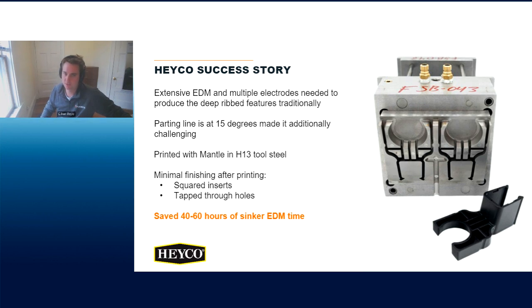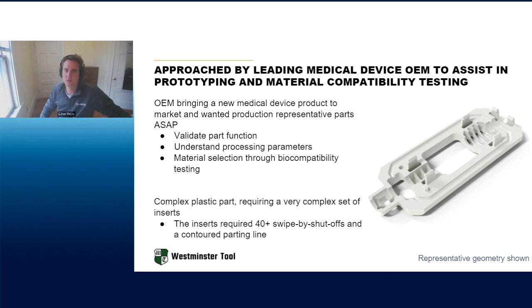After printing was complete, they just did a little bit of finishing, which was squaring of the inserts and tapping the through holes. And then this saved over 40 to 60 hours of sinker EDM time, which was reduced. Switching over to talking a little bit more on the mold making side and the product development side.